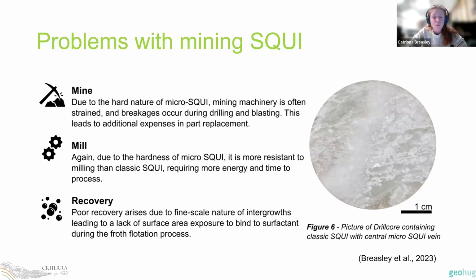And then finally, poor recovery arises as well, because if you think about this fine symplectite texture, you have your spodumene and quartz linked to one another. So in these fine particles, it's very common that there's a lack of surfactant, a lack of surface area to bind to the surfactant, so the bubbles can't actually take up the lithium to the surface.